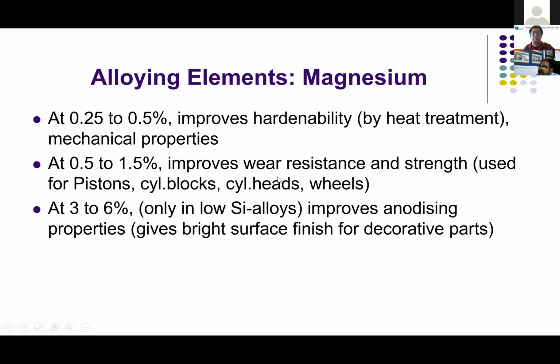0.5 to 1.5 improves the wear resistance and strength. Again, 1.5% used in pistons, cylinder blocks, cylinder heads, and wheels. 3 to 6% only in low silicon alloys improves anodizing properties. Gives a very bright surface finish, decorative parts. These are all more towards the non-automotive components.